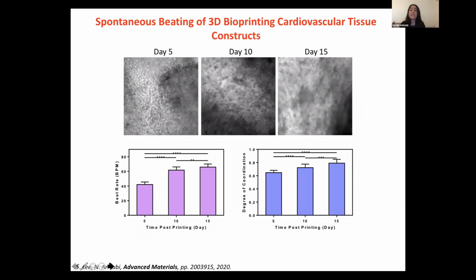One limitation of 3D bioprinting is that for sensitive cells, we are able to incorporate them in the printed structure and they are viable. But in many cases, because the printing process can be long, or due to the shear stress we put on the cells, they will not have the function that we want. And this applies more for sensitive cells like cardiomyocytes. So one characterization that we did, we measured the beating frequency, or the beating of these cells over time.